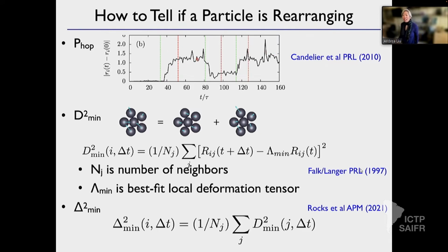One thing I have to say is that we take snapshots of the supercooled liquid, and then to get rid of thermal noise, we do one of two things. We either quench it down to 0 temperature. So we just instantaneously quench down to 0 to the nearest local minimum, and that's called the inherent structure. And we compare what's happening in the inherent structures. So if you're still in the same basin in that complex energy landscape, your particles will not have moved at all, okay? And then if you jump into another basin, you see this big change in p-hop. So that's one way to do it.